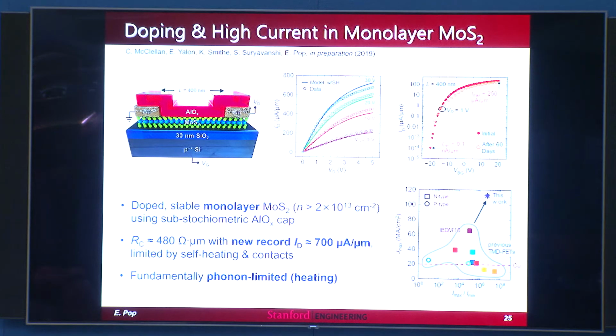But what's limiting this? Why can't we do better? For now, it's still phonon limited. Material phonons, substrate phonons, it's basically heating, right? So we could probably do better than that, even hit a milliamp per micron in a 3-atom thick semiconductor if we can figure out the thermal problem.